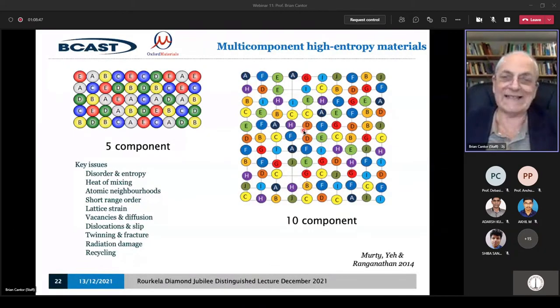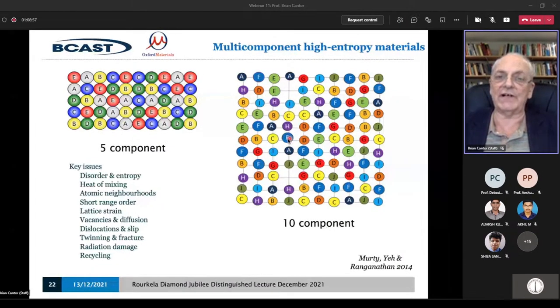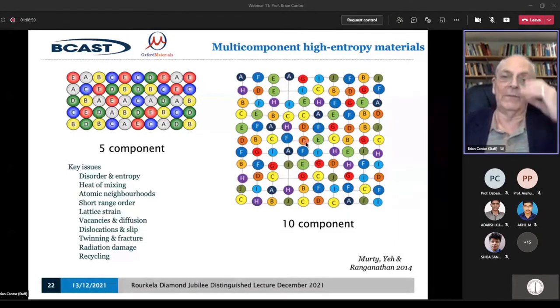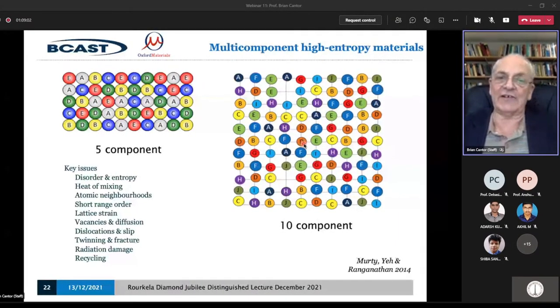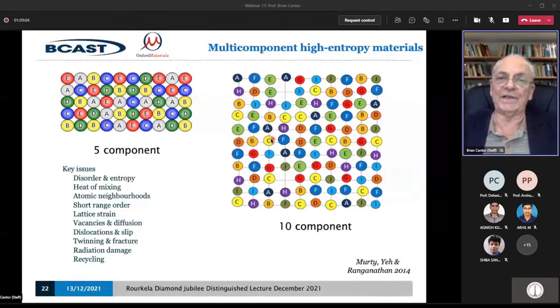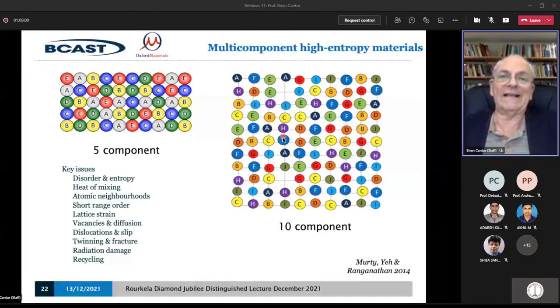I'll return to that point in a second, but notice also, on this simple way of looking at it, that each of these atoms has a different size and a different electronic structure. The most fundamental properties are the size of the atom and its electronic structure. And they're different, and how they interact will affect the local size and electronic structure in this region. So for each of these different arrangements of atoms with their first and second near neighbors, you've got a different size. And this strains and misshapes the lattice.